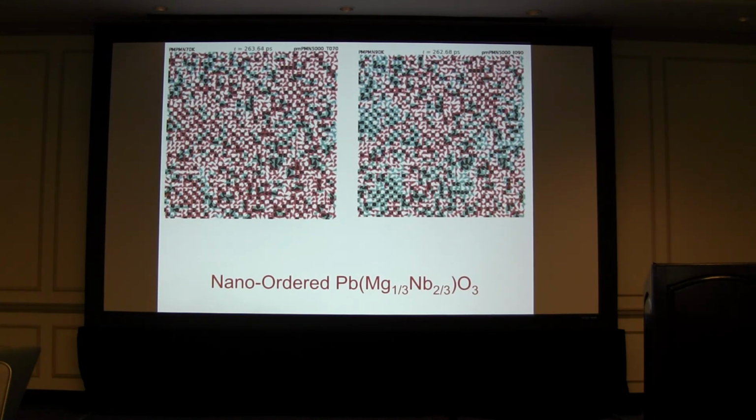So red is, I forget which is up and which is down, but one is up and the other is down. It doesn't matter, because you could turn the crystal around. And what you see is that even at rather high temperatures, the very ordered regions stay very polar ordered. And the matrix in between that's more disordered has most of the motion. And you have very much the same sort of situation at lower temperatures, except there's a lot less motion in general.